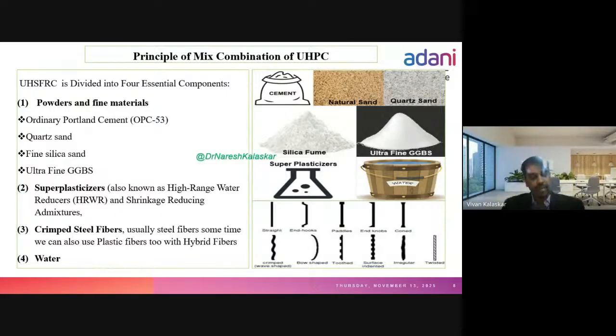Superplasticizers are very important for ultra high performance concrete, because in normal concrete we used to take a water cement ratio of 0.4 or 0.3, but in ultra high performance concrete we have to bring down the water cement ratio to 0.15. So to get the proper fresh properties of concrete, we need an excellent superplasticizer. So superplasticizers play a major role in ultra high performance concrete.